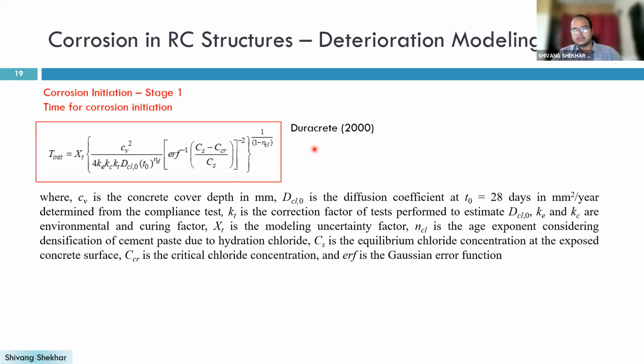for a reinforced concrete member. We can see that it depends on surface chloride concentration, on a critical chloride concentration, and on your cover depth. What is the concrete cover depth? The larger the concrete cover depth, the more the initiation time, and the lesser the corrosion, you can say, if you take a service life. It also depends on several environmental factors.